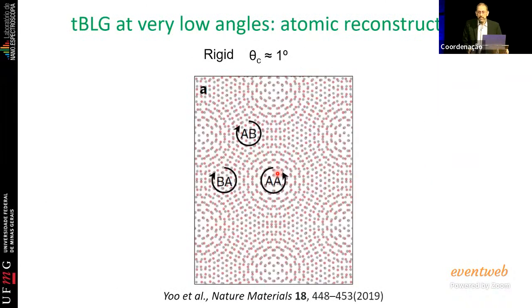Okay, and that's not everything. If you go below 1 degree, you also have something very interesting happening. Here you have the 2 layers of the bilayer graphene represented by the gray and red dots. Each dot here is 1 carbon atom. And if you notice, at those regions is where 1 atom of the top layer, let's say the gray, falls exactly on top of the atom from the bottom, that is the red. So this would be called the AA stacking. You have one exactly on top of the other.